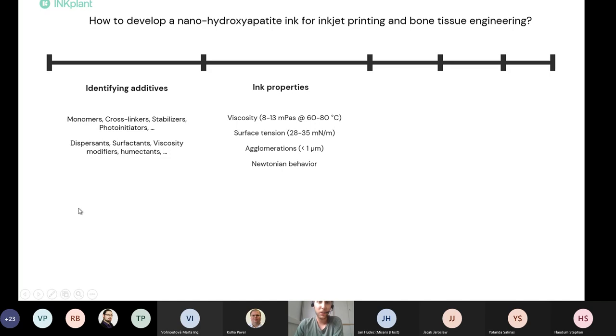So if this stage is more or less completed, one can start by formulating first inks. And when you think about an inkjet printing process, there are basically 3 to 4 major challenges that need to be overcome. Inkjet printing is very demanding when it comes to the rheological properties of the ink.